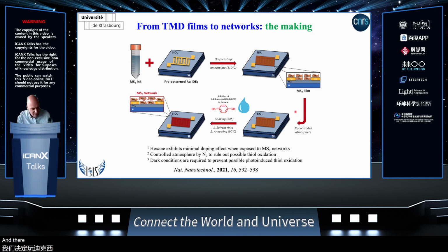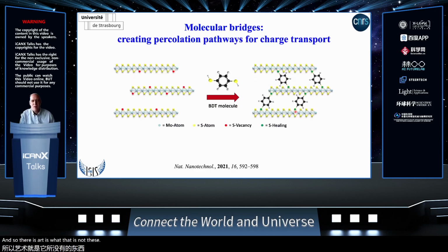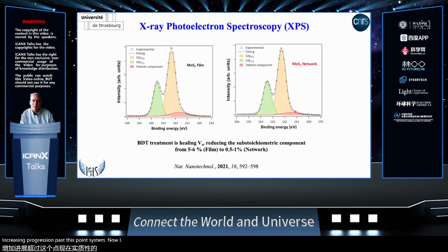And so the result is what? Well, the cartoon is the following: the idea is that this kind of molecule bridges adjacent flakes, creating percolation pathways for charge transport. Now, let me prove that this was really happening. One piece of evidence we got is from the X-ray photoelectron spectroscopy measurements. On the left, I always place the films which consist of flakes that are disconnected, and on the right, I have the network where the flakes are covalently connected.